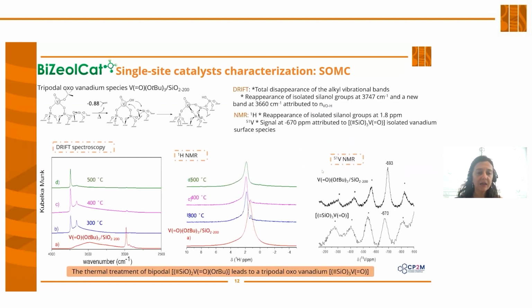Okay, this reaction of the preparation of the bi-tripodal single-site catalyst was characterized by DRIFTS and NMR. In the case of the DRIFTS, if we see the first red line, in which we have the bipodal species, as we increase the temperature, we observe one band which is related to the silanols, and another band which is related to the vanadium hydroxyl signal. So what we can observe here is that the butoxyl or the alkyl part goes off, and the vanadium gets grafted onto the support.